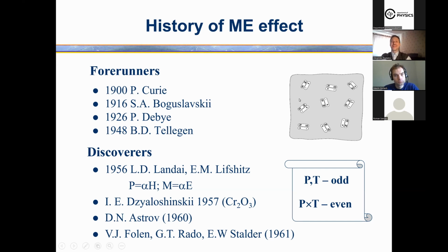He was an engineer, so it was a practical recipe. And as soon as we apply an electric field, the electric particles orient, and as they are coupled to magnets, the magnets also orient, and vice versa. A magnetic field also can orient these particles. But remarkably, there were no attempts to make this media until the natural magnetoelectrics were found in the 1960s.